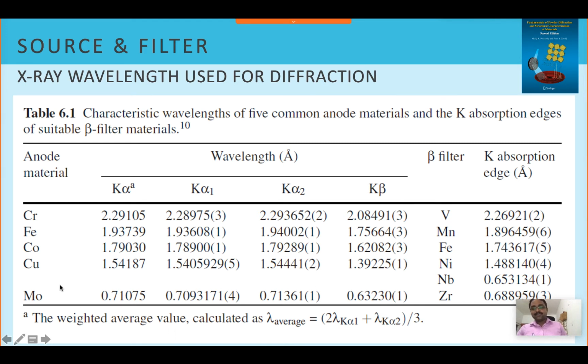So in earlier days when we have, for example, iron in some element, we usually go for cobalt because there was a fluorescence effect taking place. So depending on the samples, in earlier days we would be using cobalt, chromium, different types of wavelengths. Now the commonly available wavelength is copper K alpha, that is generally written as 1.5406, the average of this one. How can we average this out?